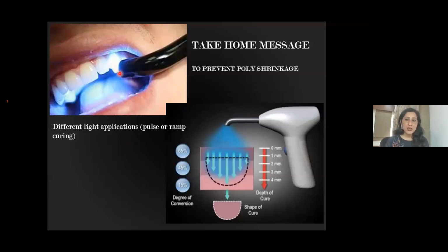So I would also suggest that whenever you start your light curing, always use soft start, pulse or ramp curing, because your lights have this. The newer lights have these functions of ramp curing, pulse curing, soft curing, which means that first a softer light intensity is imparted to the composite so that it may slowly and steadily form into a polymer. And when the free radicals are generated, they start forming the reaction, and the monomer starts forming into a polymer.